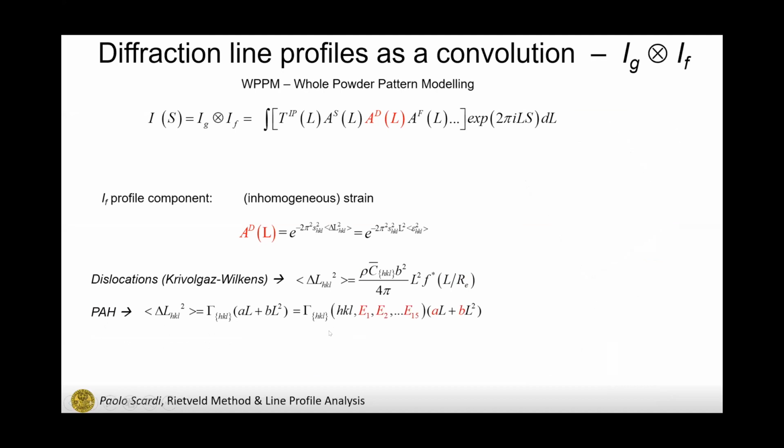Okay, with this model, it is possible to refine the coefficients of this invariant form that is called gamma, which is identical with the average contrast factor, but now you have three coefficients, the number of which is determined by the crystal symmetry of the phase, and in particular according to the Laue group of the studied phase.